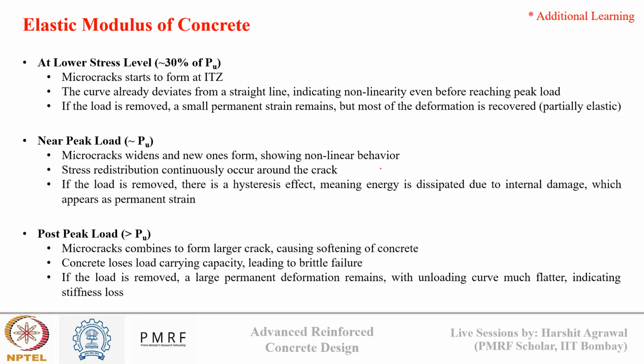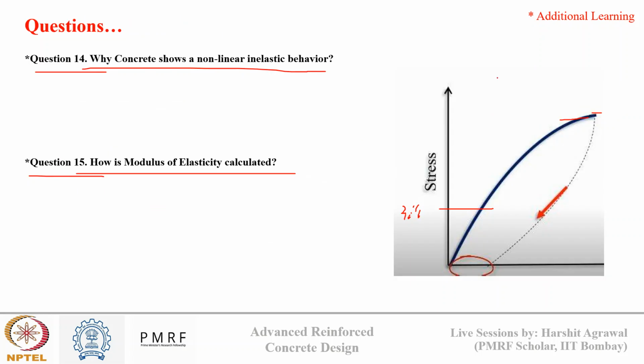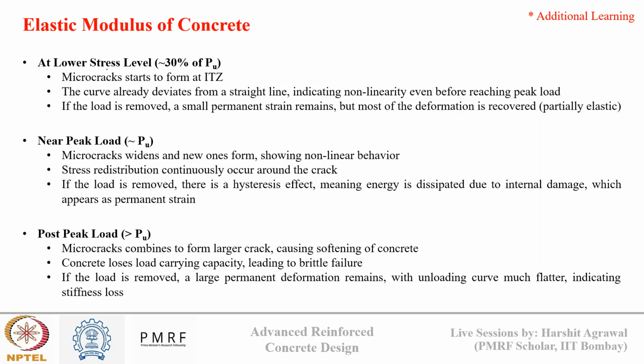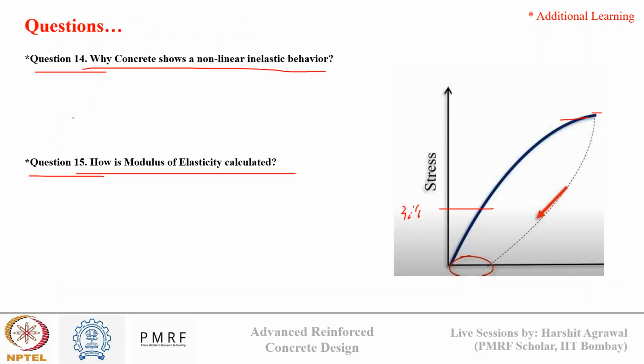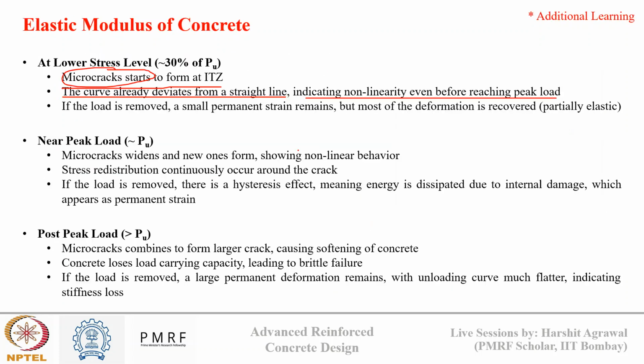So when the load is applied up till 30% of this peak load, what will happen? Microcracks start to form in the ITZ, which we have already discussed when we talked about how failure occurs in concrete. So this curve already deflects from the straight line, which indicates non-linearity is reached. Why? Because of the micro cracking happening in the concrete. And here if we remove the load, we will see only a small permanent strain will remain. Most of the deflection will be recovered because there are still only micro cracks in the ITZ.